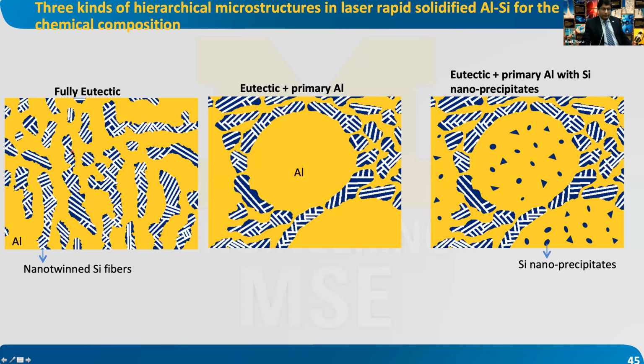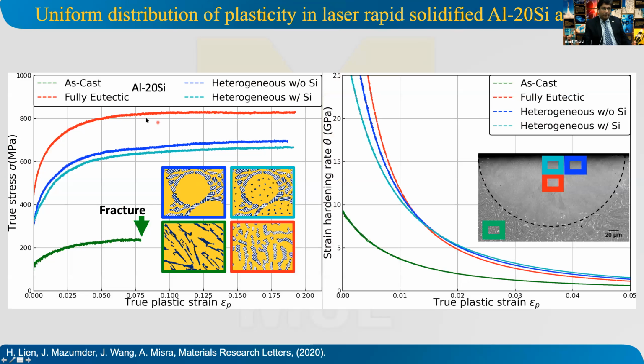One is that silicon shape has changed. It has become fiber. Second is very fine. The very fine part was expected. The part that was surprising was the nano-twin structure and the fact that in aluminum dendrite, you see these very fine silicon precipitates. What does that do to the properties?